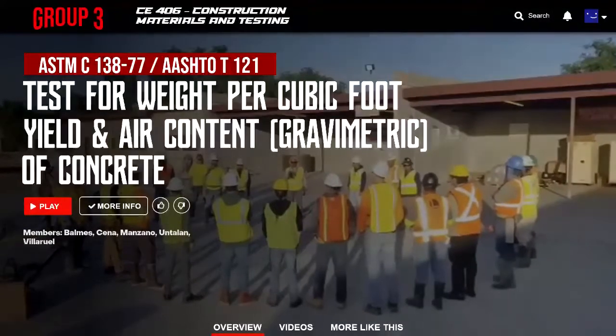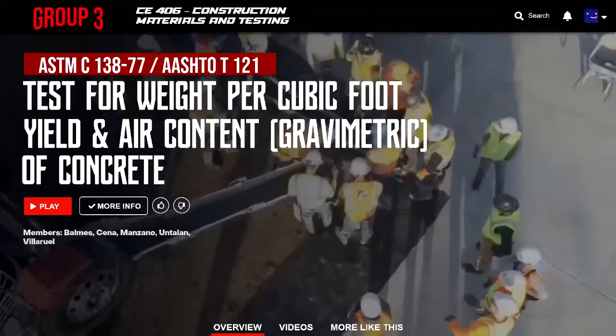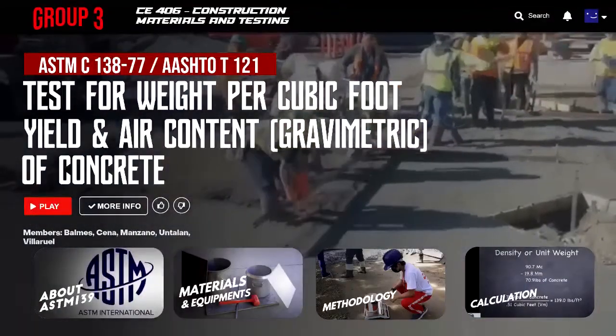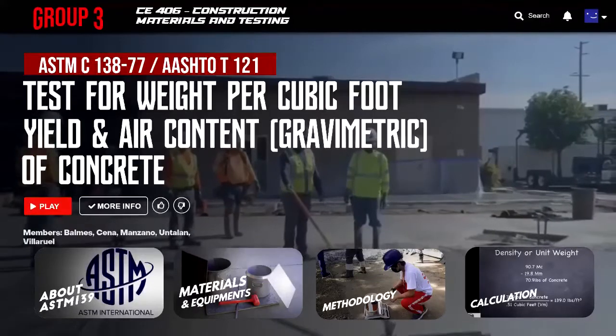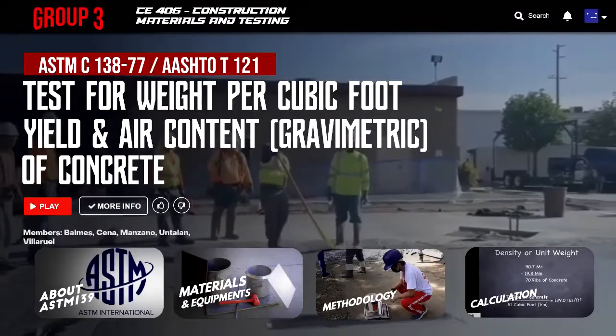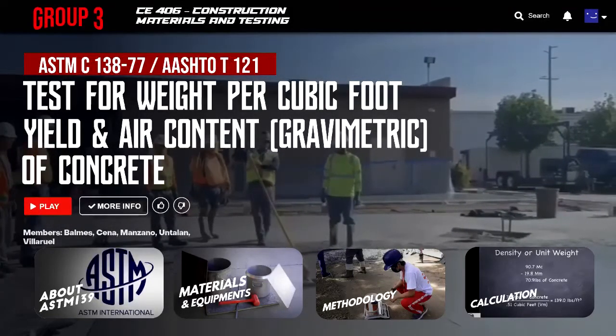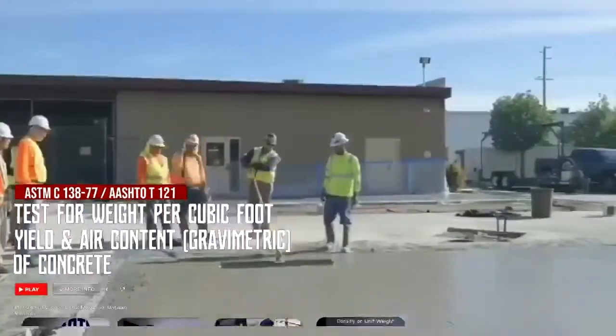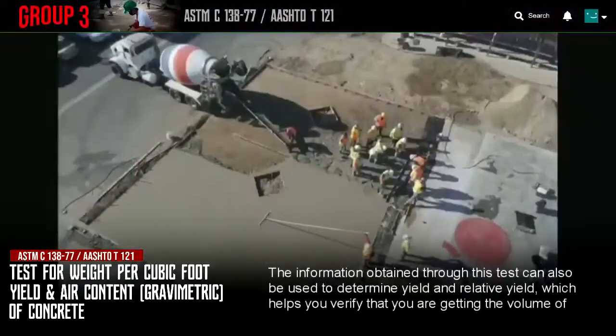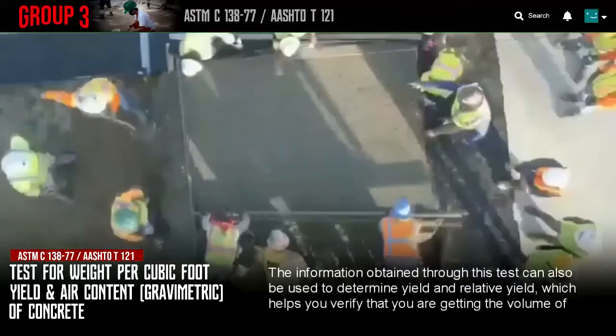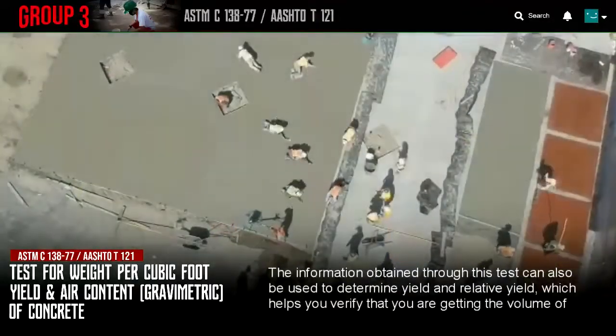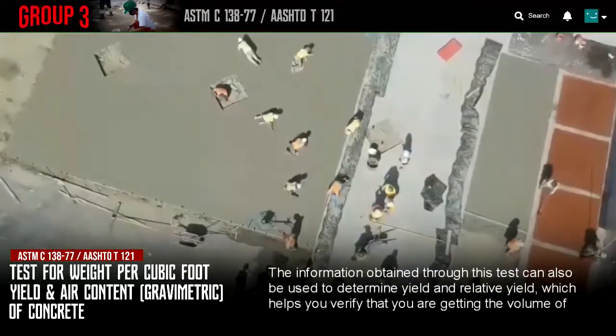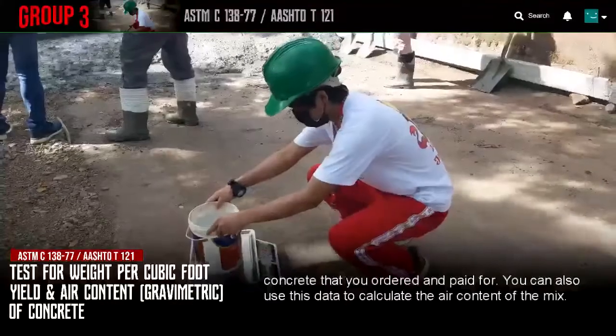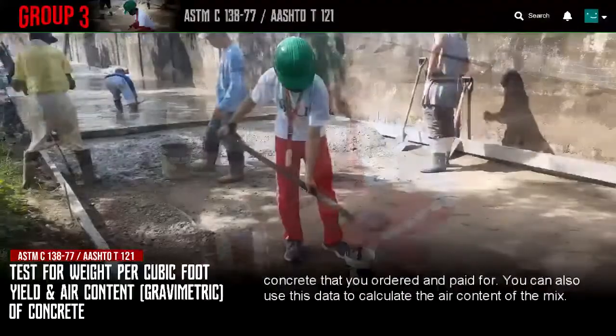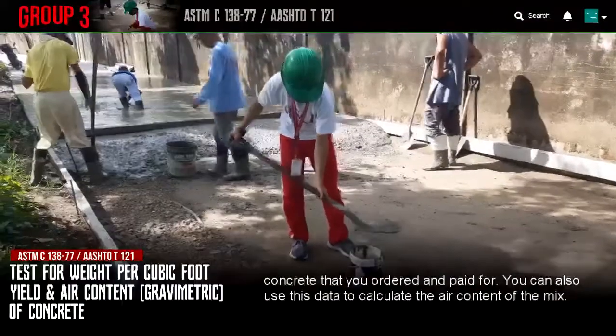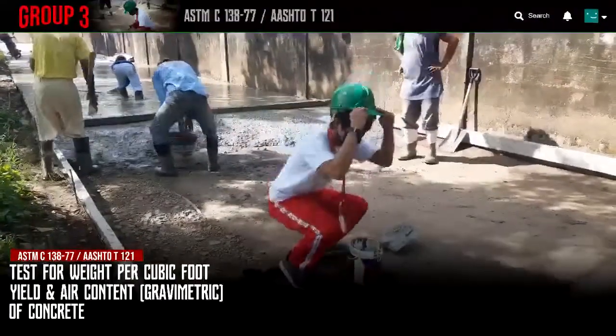This test method covers how to determine the weight per cubic foot of a freshly mixed batch of concrete so that we can get the data needed, like the yield, cement content, and the air content of the concrete. The information obtained through this test can also be used to determine the yield and the relative yield, which helps you verify that you are getting the volume of concrete that you ordered and paid for. You can also use this data to calculate the air content of the mix.